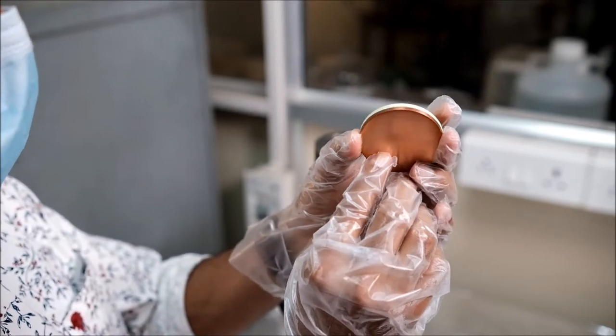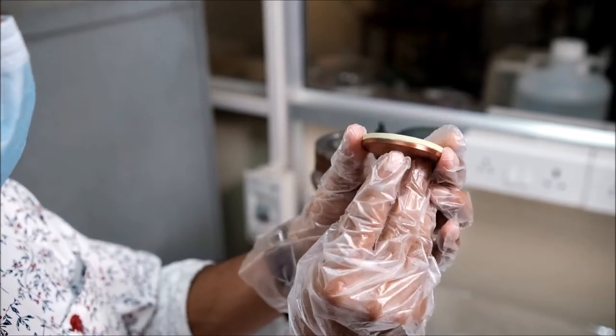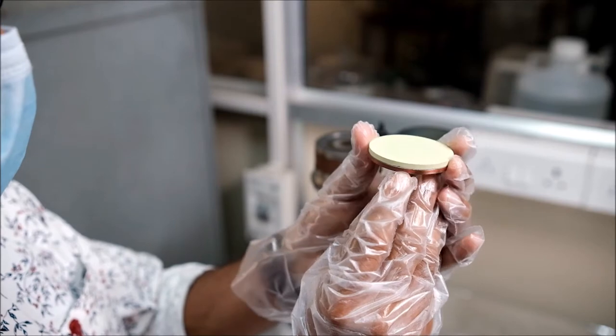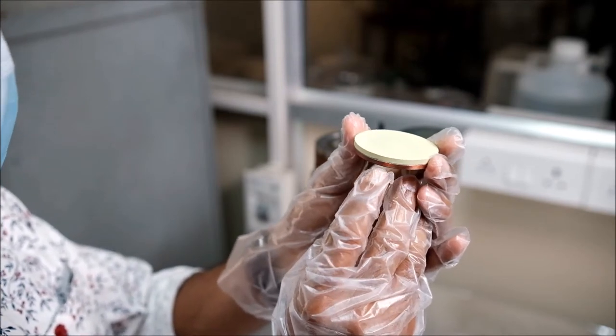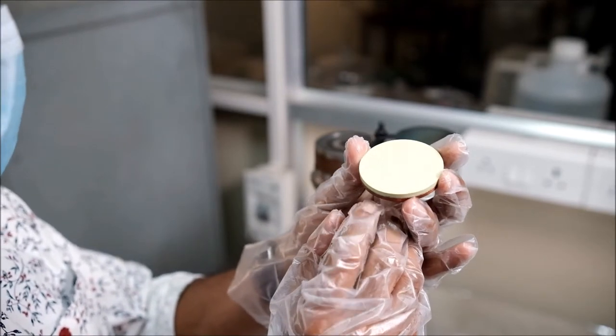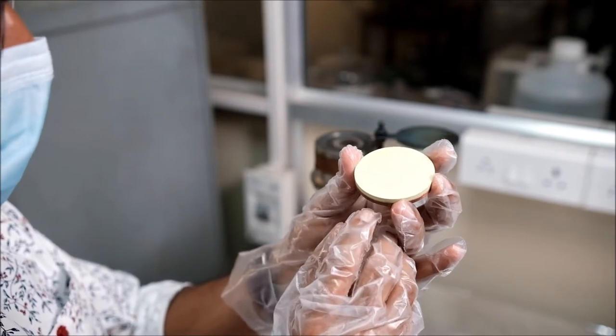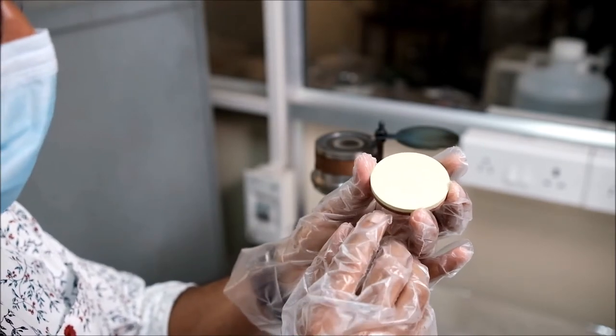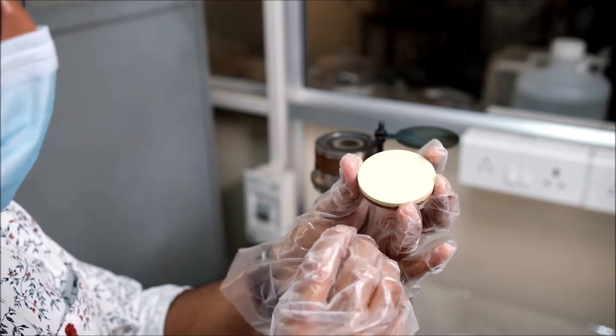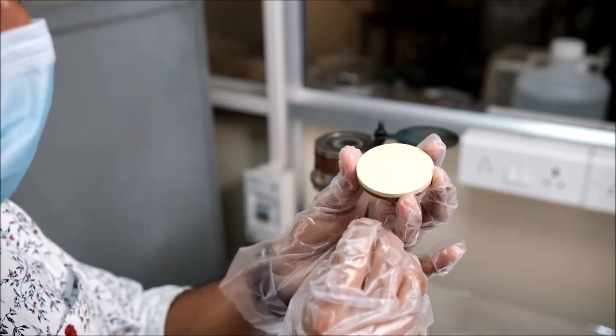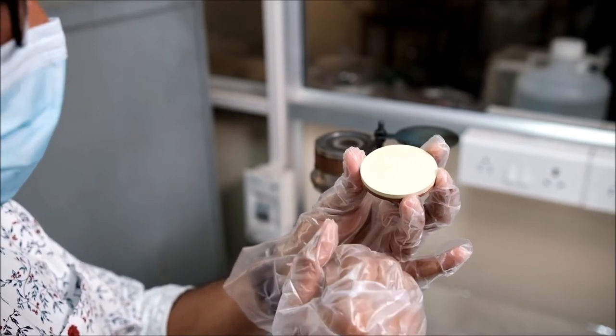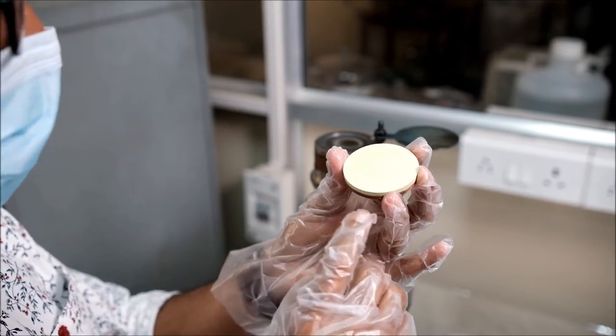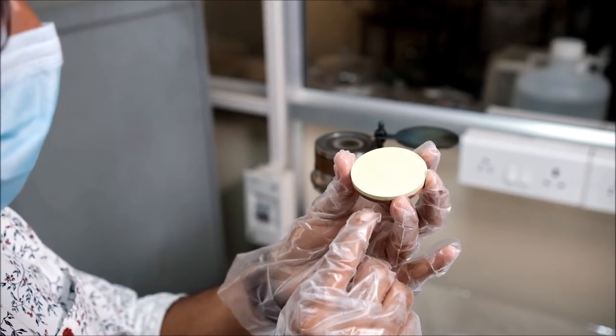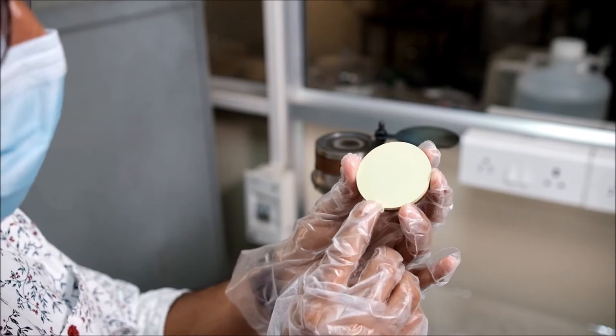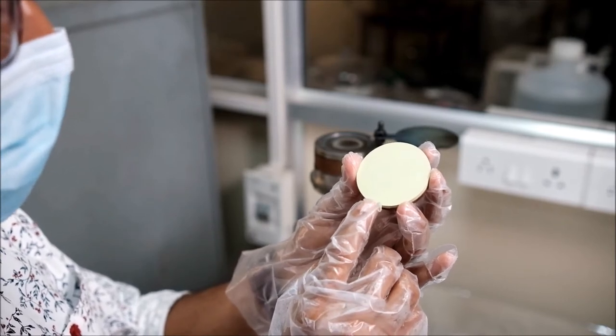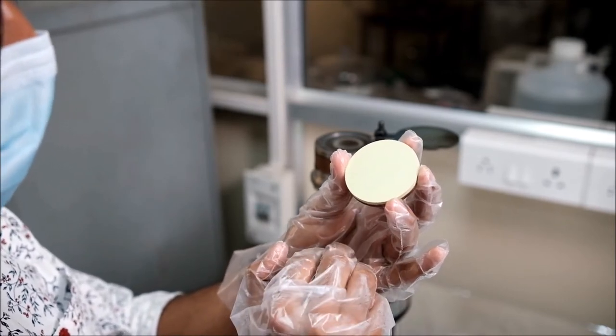And the target material is attached to the backplate with silver paste or indium paste, because these are good heat conductors. In the third step, to mitigate this heat dissipation, we also increase the RF source very slowly so that it gets enough time to dissipate the heat. If you don't follow this process very carefully, then the target may break. And this is quite common for oxide target deposition.